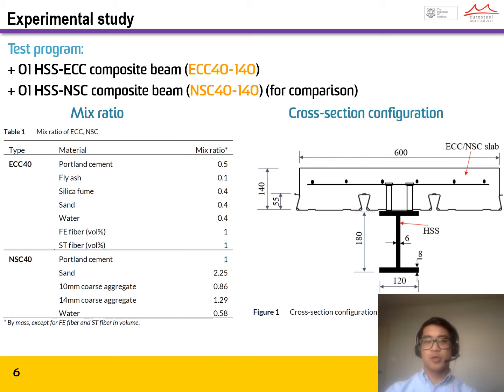The high-strength steel beams at the bottom were designed to satisfy the compact section requirement indicated in the European standard and Australian standard. They were manufactured by welding high-strength steel plates together. To construct the ECC and NSC slab on top, one mix of ECC and one mix of NSC were used. The materials used for the ECC mix included cement, fly ash, silica fume, local dune sand, water, PE, and steel fibers. For normal strength concrete, cement, sand, coarse aggregates, and water were used.